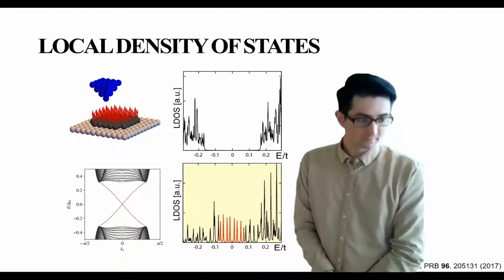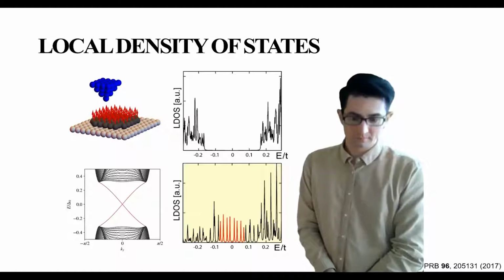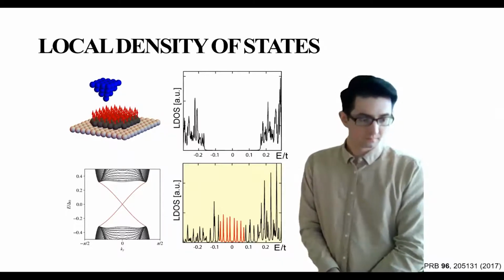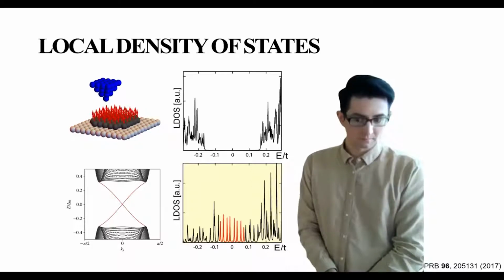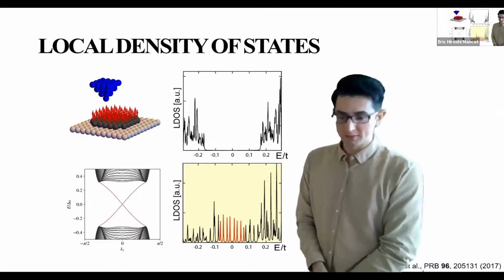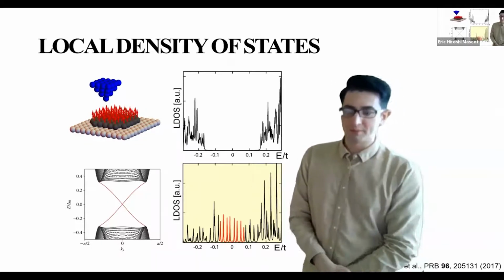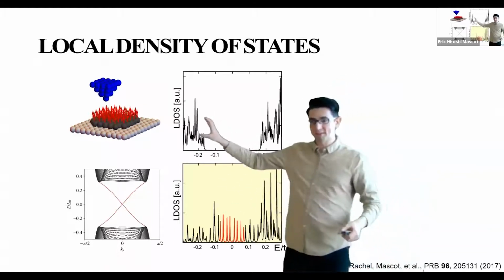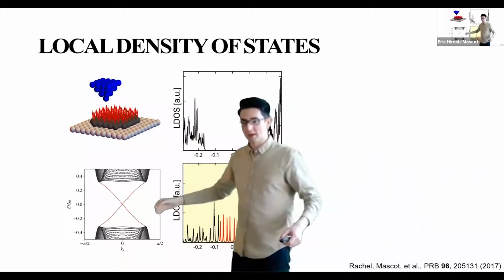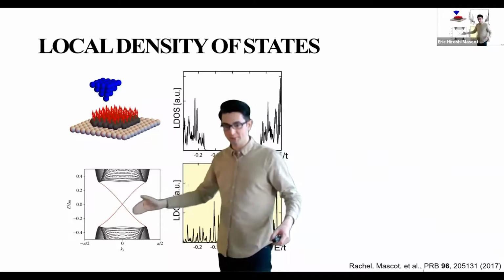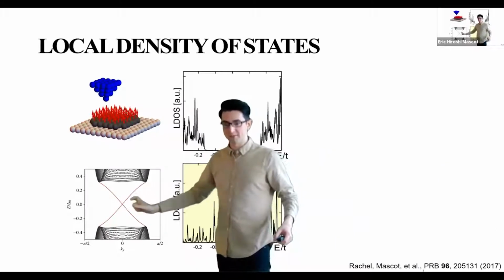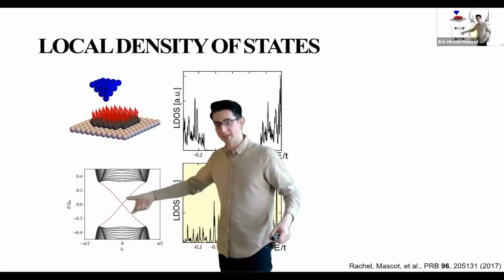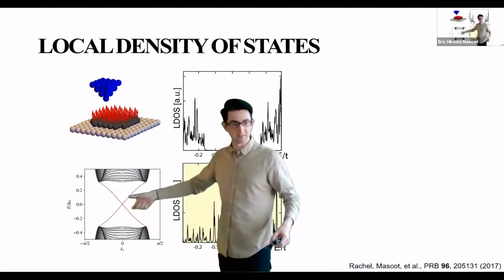How do these peaks on the bottom plot, the red peaks, correspond to what I see on the left plot? So this is a finite size island, and if we were to have discrete K points, these would be evenly spaced in K, and so you would have evenly spaced in energy.